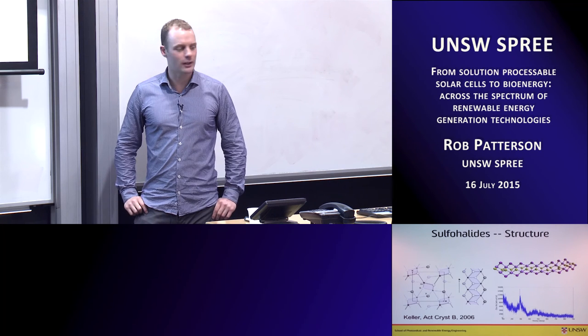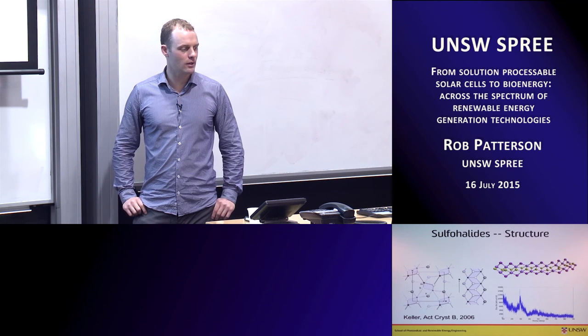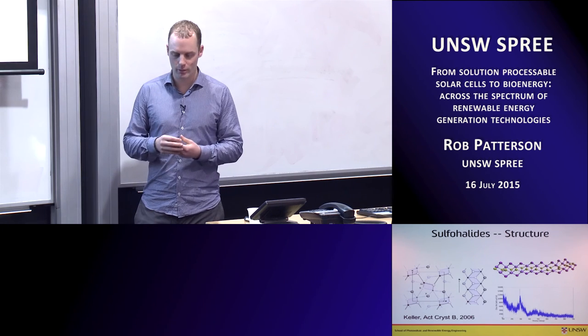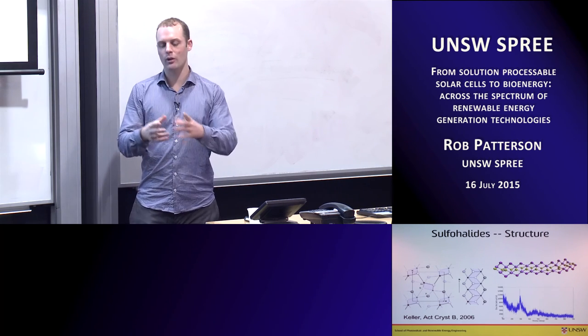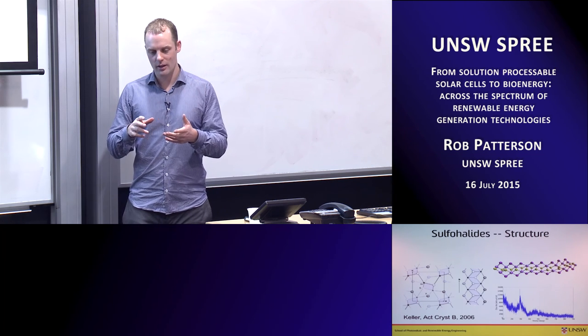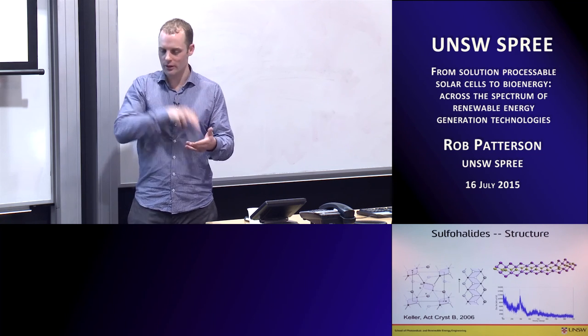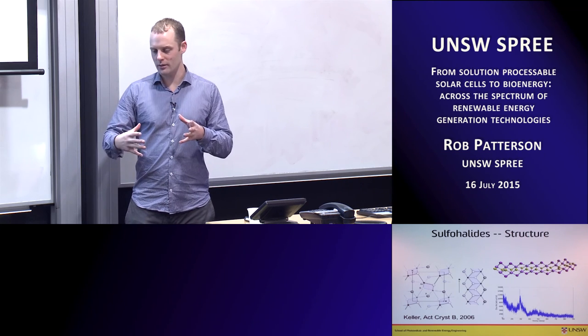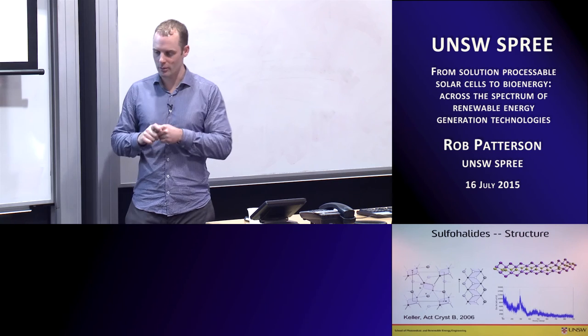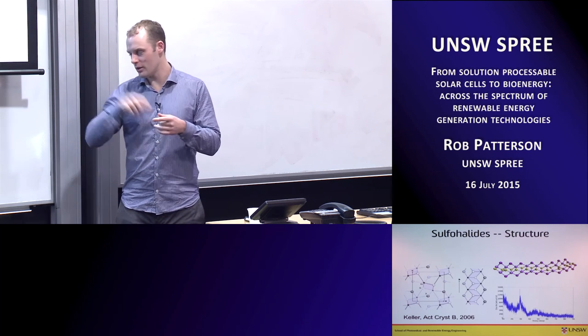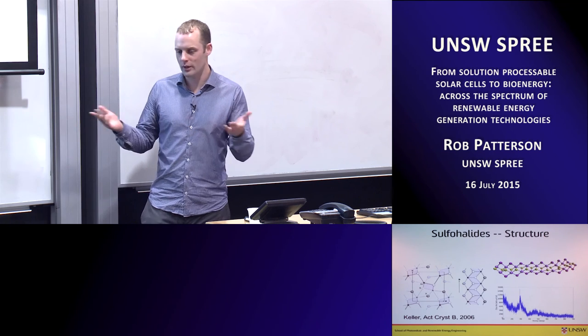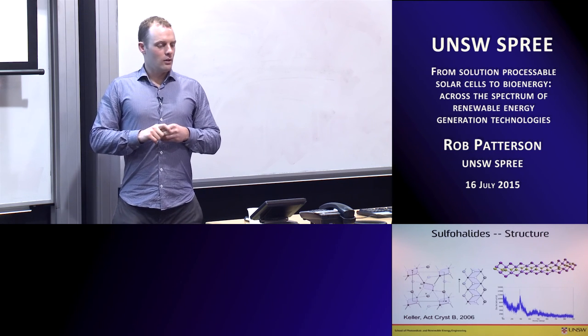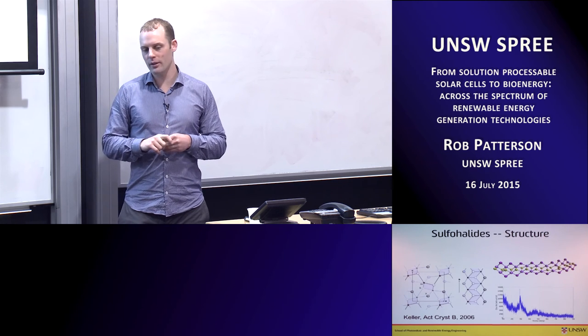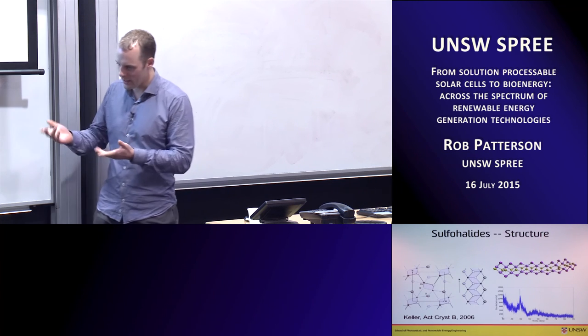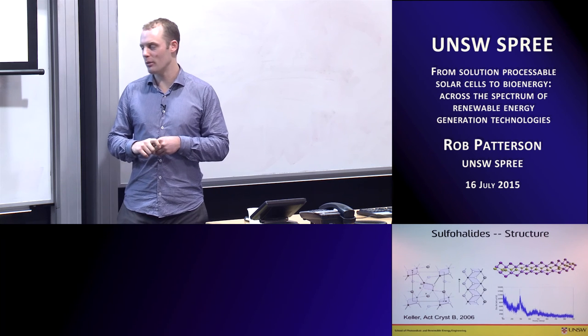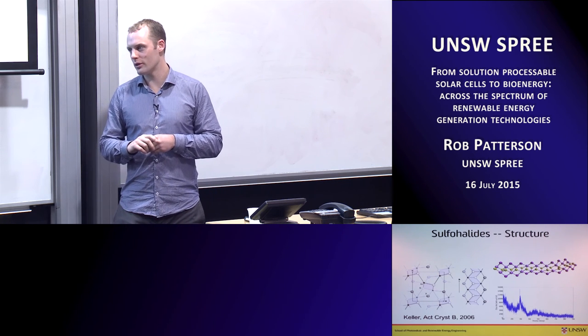But yeah, transport in these materials is a big question mark. I've been discussing this with people, and if you have enough surface coverage such that you have a high enough density of these defect states, then you might imagine hopping from defect state to defect state around the surface. And if the other surface is close enough, just like in our nanoparticle solar cells, you could get hopping from dot to dot by tunneling or whatever you want to call it. So there's potential for transport, but I think photocatalytic approaches make a lot more immediate sense. So that's the first thing that we were interested in trying.